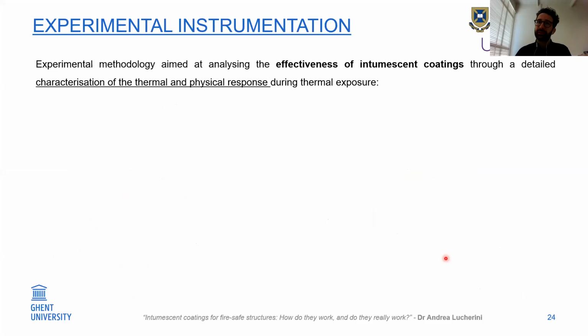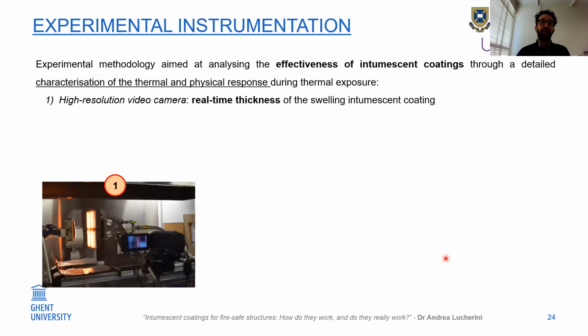In terms of instrumentation, the experimental methodology and setup were designed to analyze the effectiveness of intumescent coating through a detailed characterization of the thermal and physical response during thermal exposure. In particular, I was trying to get as much information as possible to characterize the performance of the intumescent coating when it is exposed to fire. First, I used a high-resolution video camera placed on the side of my test samples, so that through video analysis I could quantify the real-time thickness of the swelling coating.